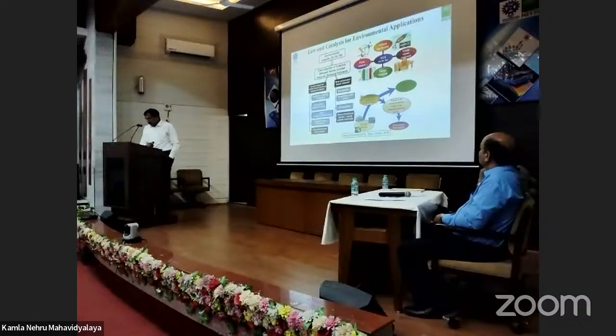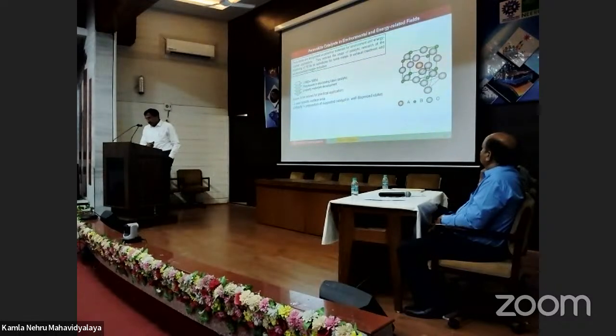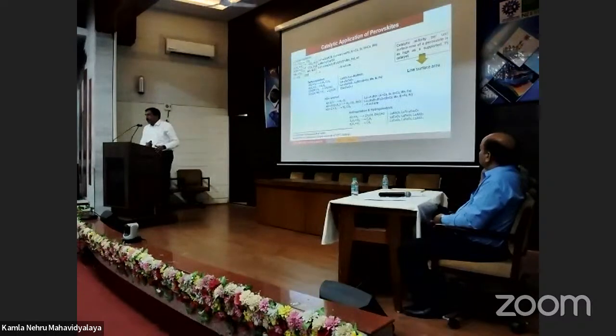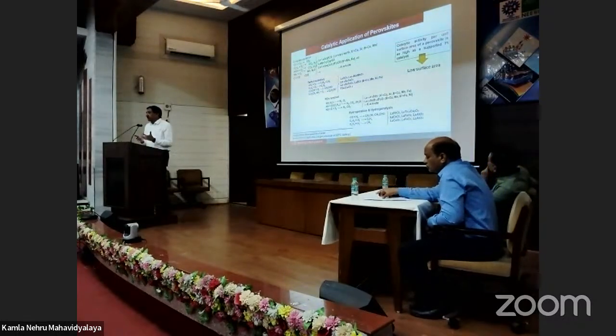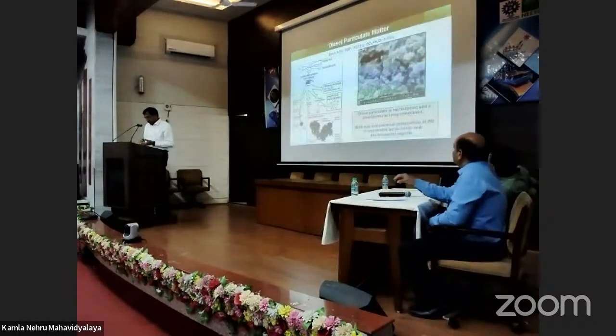NIRI has been working quite long on non-noble metal-based catalysts for automobile and other applications. Perovskites are mixed metal oxides, and you don't have to use noble metals. You can tailor them, and there are many advancements. This is from Professor Teraoka, who was one of the best. Unfortunately, we lost him about 5 years back. These are the different reactions for which you can tailor the composition of perovskite-based or mixed-oxide-based catalysts. You can design them. But there are limitations with platinum. With platinum, you can prepare different particles and induce some kind of functionality, but with perovskite, you can do a lot better.